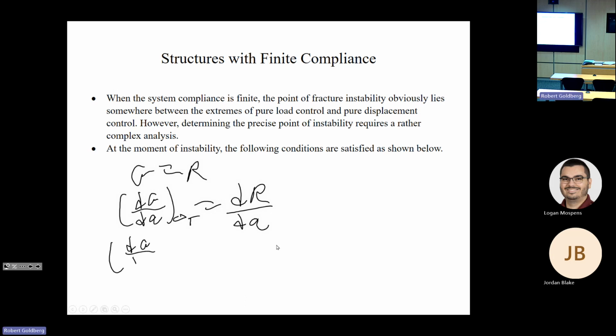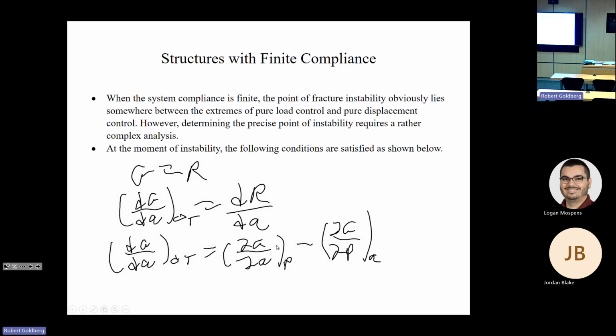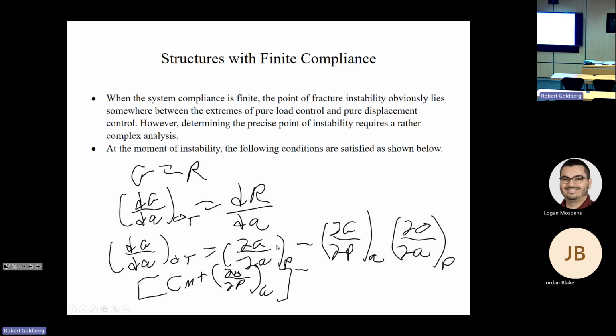And you can derive, we won't go through it here, it's a complicated analysis, that this rate of change is equal to the partial derivative of the strain energy release rate with respect to crack size, for the load, minus the partial derivative of G with respect to load for crack size, times the partial derivative of the displacement with respect to crack size for the case of the load, all multiplied by the compliance plus the partial derivative of the displacement with respect to the load for crack size, and this is all inverted.